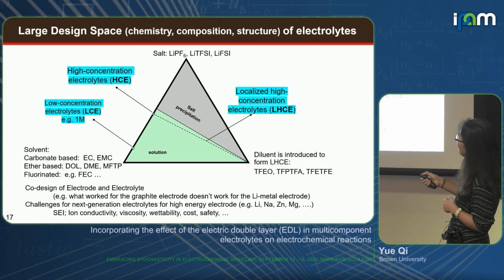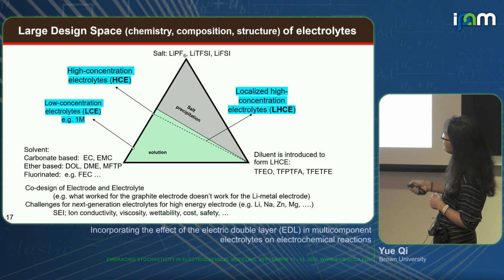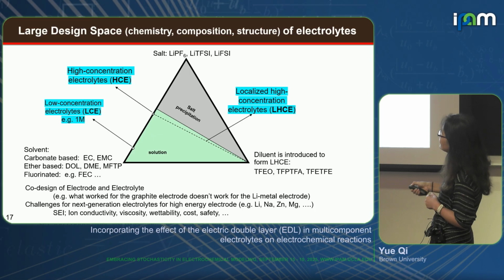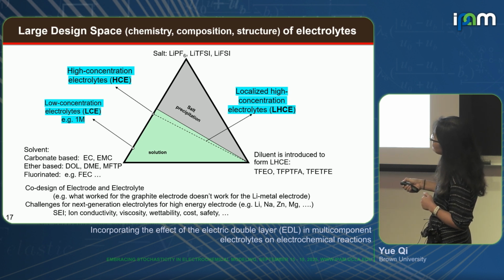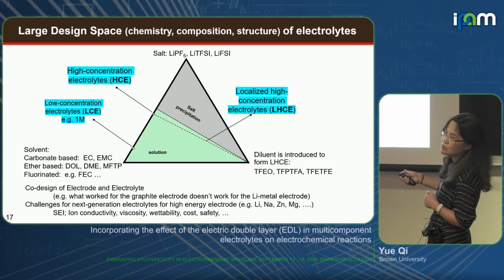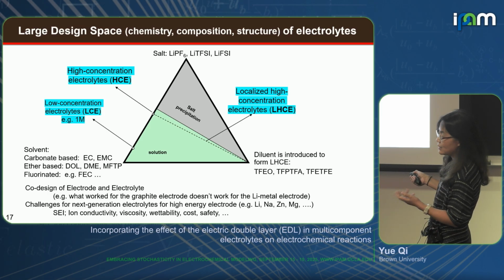So you can mix salt and the solvent, and this is a materials science way to present electrolyte. If we're dealing with very dilute electrolytes, we're increasing our concentrations, we're reaching our solubility limit. And different solvents may have different solubility limits, right? After you make these high concentration electrolytes, they don't flow well, and that's why a diluent was added to try to make things flow better.